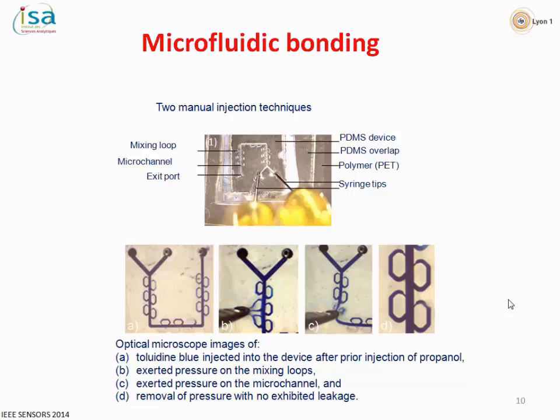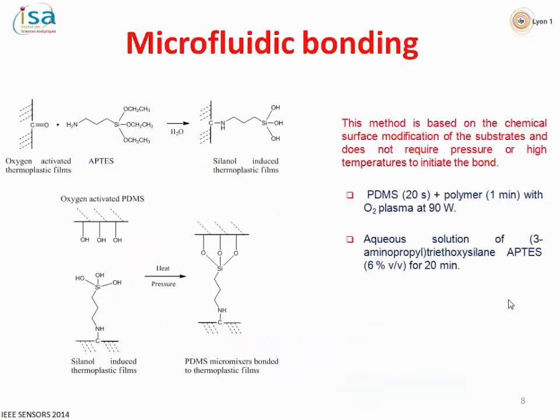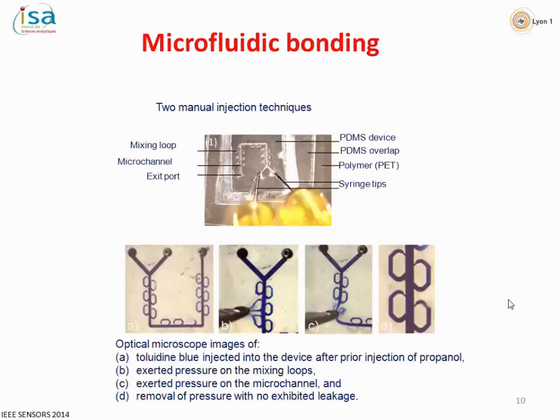In fact, we start here, and not only that, we apply pressure here in different regions in order to see if we can block the channels or loops, and we can see after that we have a nice mixing at the end. That means we have no leakage of our polymer, and the silane part is well done. However, this part is critical, because we must know at which stage, if not, we can have some polymerization of silane, and we will not have a self-assembled monolayer.